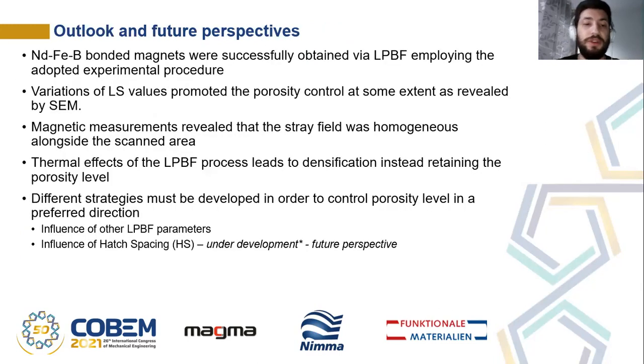The outlook of this present work is that neodymium bonded magnets were successfully produced by laser powder bed fusion, employing the adopted experimental procedure. Variations of laser scan speed values promoted porosity control to some extent, as revealed by SEM. Magnetic measurements revealed that the stray field was homogeneous along the scanned area. The thermal effects of the laser powder bed fusion process lead to densification instead of retaining the porosity level.